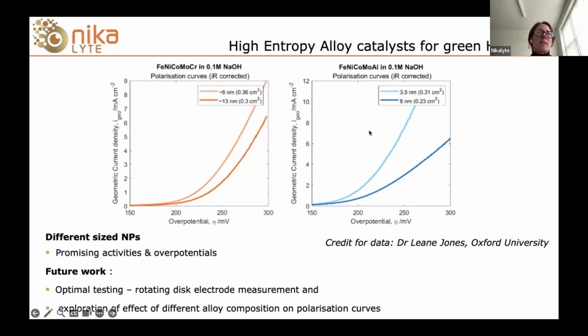And we've compared the effect of size for those two different alloys. And what we see, interestingly, is that the smaller nanoparticles perform better in both cases. For the chrome alloy, the 6 nanometer nanoparticles perform better. In the aluminium case, it's the 3 nanometer nanoparticles that are better.